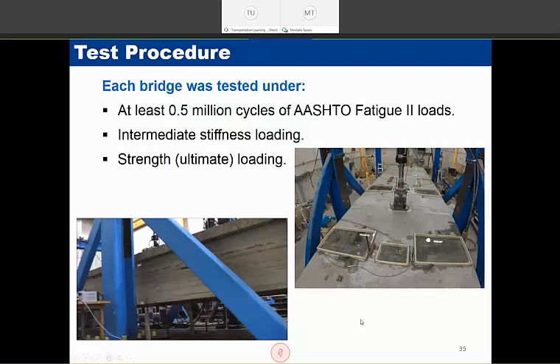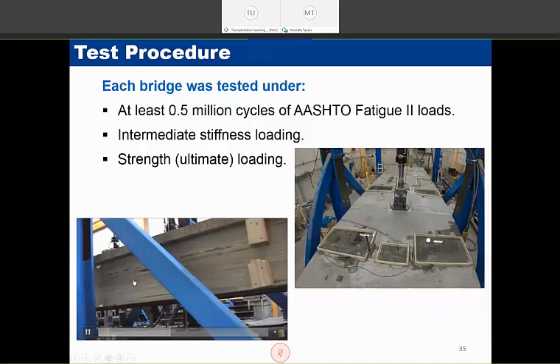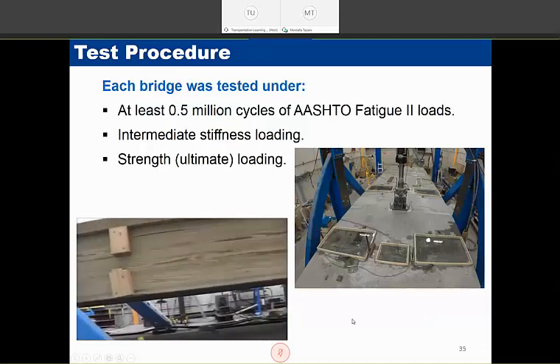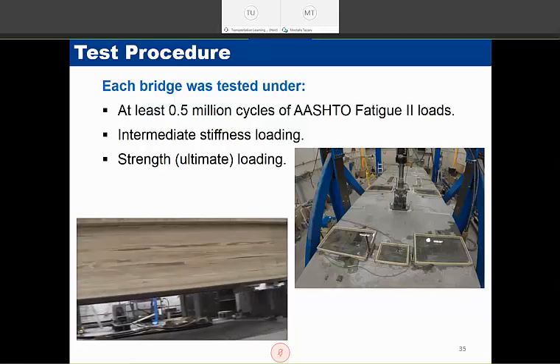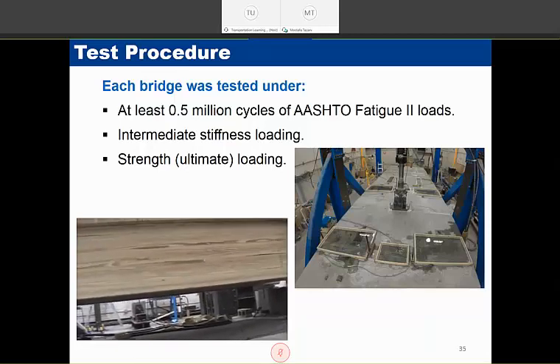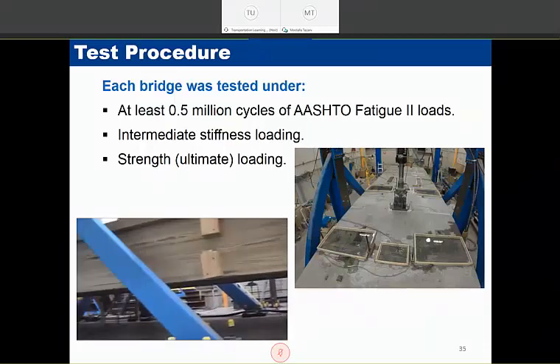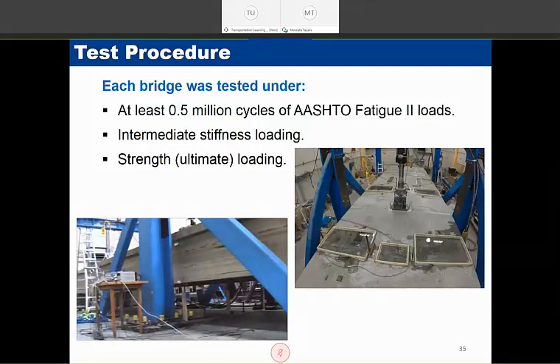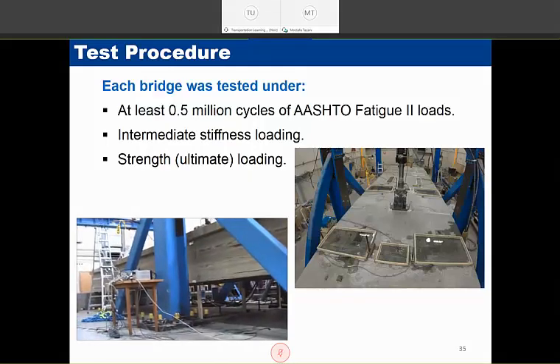Here on this slide, I would like to show you the fatigue testing of the timber bridge. You can see that because the stiffness of a timber bridge is not usually that much, we were able to see large deflections at the fatigue level. We tested each of the three bridges with at least 500,000 cycles of AASHTO fatigue 2 loads. We also tested for intermediate stiffness to make sure that we are capturing the overall behavior of the bridge. And after the fatigue testing of each specimen, we also pushed the bridge to failure to evaluate its ultimate behavior.